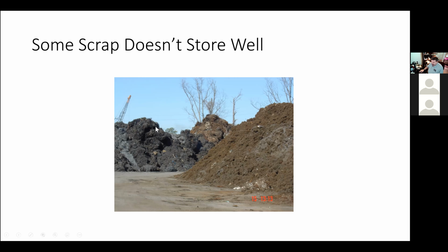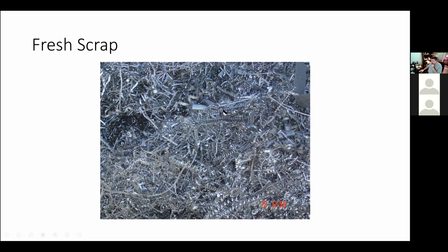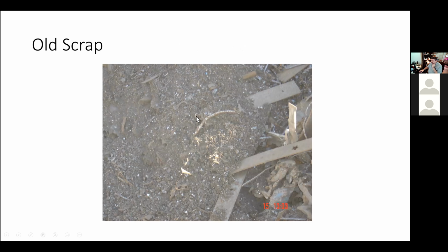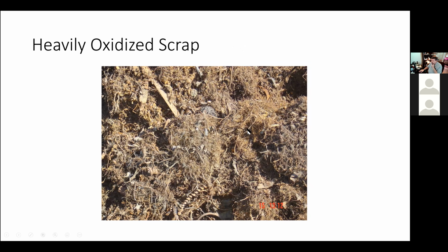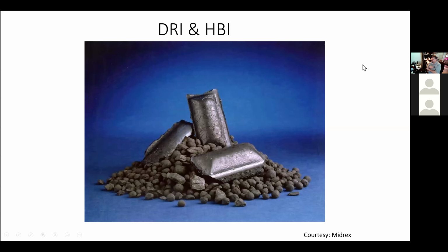But you can see this is on the left here, you can see material that was just delivered. And on the right, you see material that sat for 2 or 3 days. And so again, you have to use it very, very quickly, or you'll take a lot of yield losses. And when this oxidizes, it takes a lot of energy as well as a reductant like carbon to try to recover that iron oxide and get it back as metallic iron in the steel bath. So those are some of the challenges we're facing.